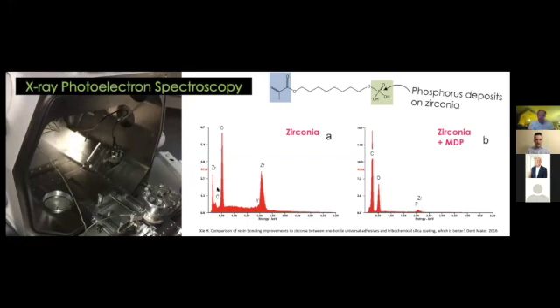And all they did was they took some zirconia, they did XPS, and they found that, of course, there's going to be zirconium and oxygen on that surface. But then they took the zirconia and they put some MDP on there, and then they rinsed it off, and then they put it on the XPS, and they found that, when you did XPS, you found some phosphorus in there, and that phosphorus had to have come from some MDP that had stayed bonded to the zirconia. So that's the simplest test.